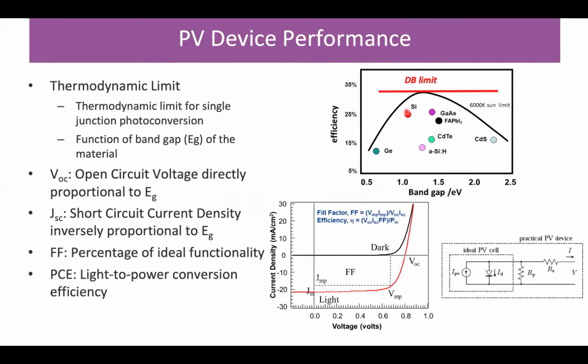And if you look at things like silicon, which are well-established technologies, or gallium arsenide, which is really the best semiconductor for the solar task from a number of different perspectives, you can see that there's quite a bit of headroom, and a lot of this loss is due to practical considerations, because you want things like wires to transmit the photogenerated carriers and things like this, and that ultimately does limit your device performance.